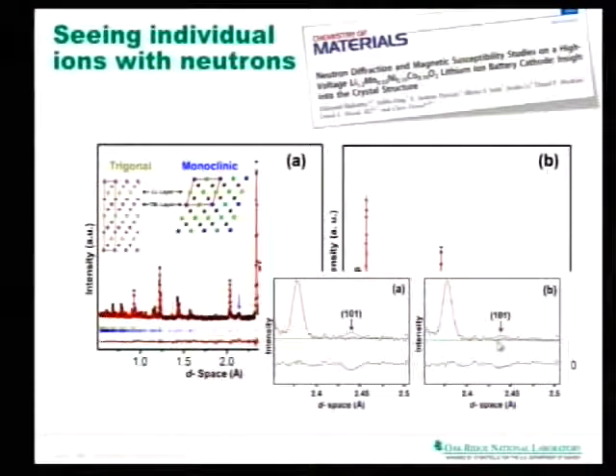And all kind of other things happen in other parts of the pattern, which really makes it tricky. But as I'm, for example, taking some nickel and lithium and I switch them over, that peak gets smaller and smaller as I do that. And we could determine that I have about a 3% swap. So about 3% of my ions are swapped, and I have nickel sitting on lithium places and lithium sitting on nickel places.